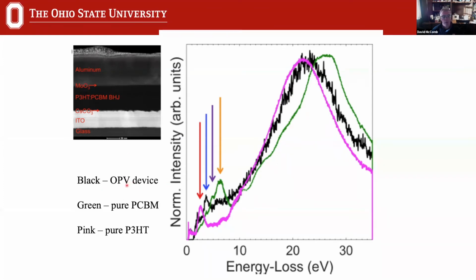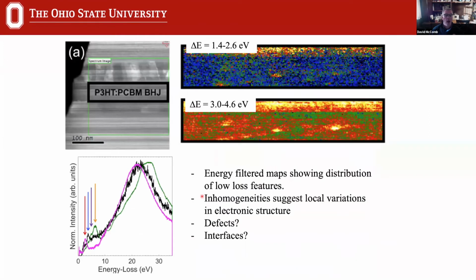So this is from the OPV device in black, and we compare that with our spectra from our pure phases. In this case, it's a substituted C60 and a substituted thiophene system. So these are just averaged over relatively large areas. And then we can pick this peak that we've indicated by the blue arrow, and then we can look at how that varies spatially through our layer.